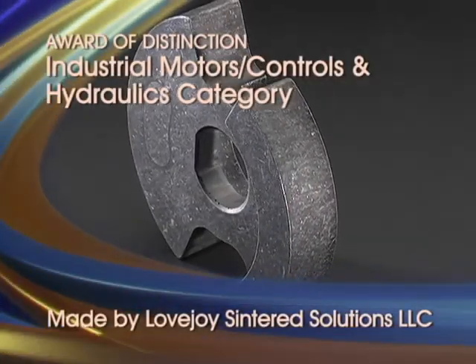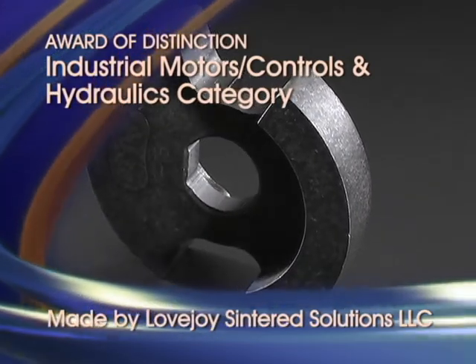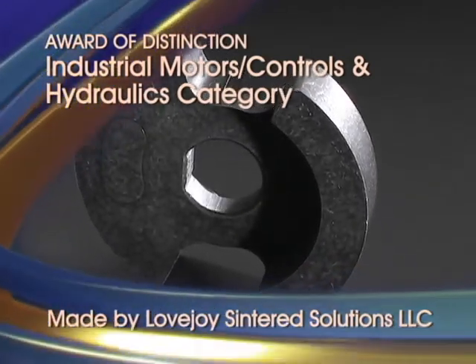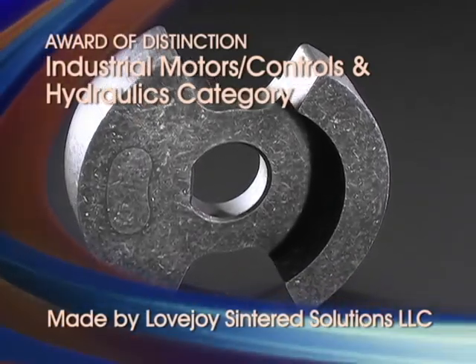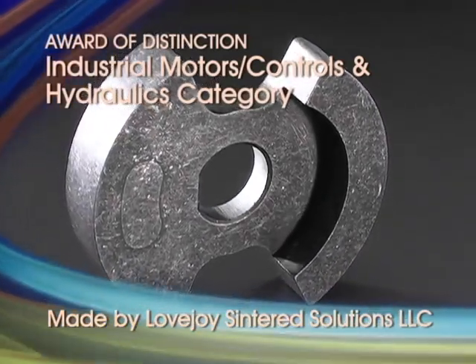Lovejoy Sintered Solutions LLC has received 2 awards of distinction in the Industrial Motors Controls and Hydraulics category. The first award is for a rotating machine counterweight used in a refrigeration compressor for truck trailers. Formed to a density range of 6.7 to 7.0 grams per cubic centimeter, the PM steel counterweight has a tensile strength of 47,000 psi and a 57 to 60 HRB hardness.